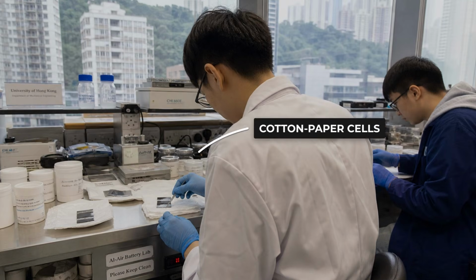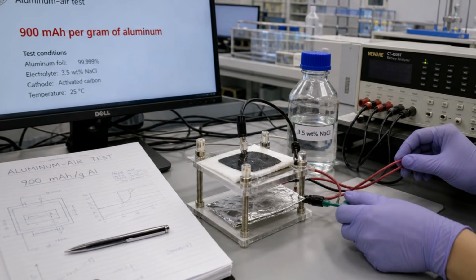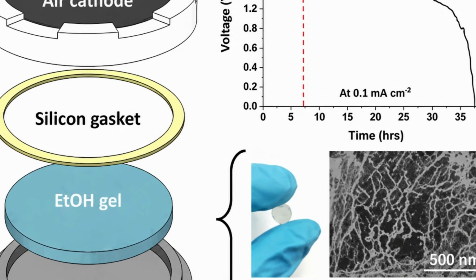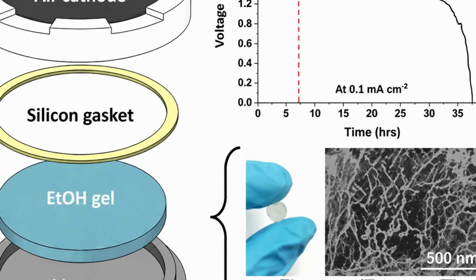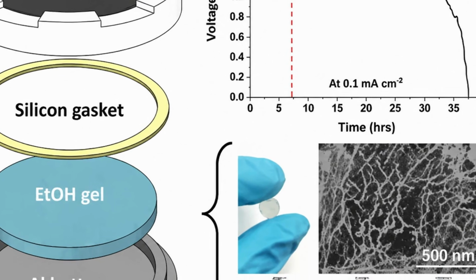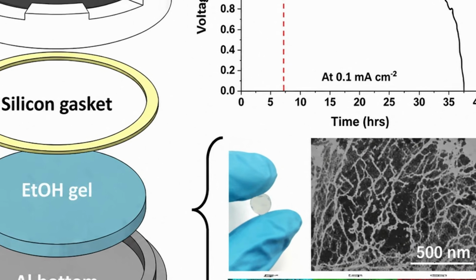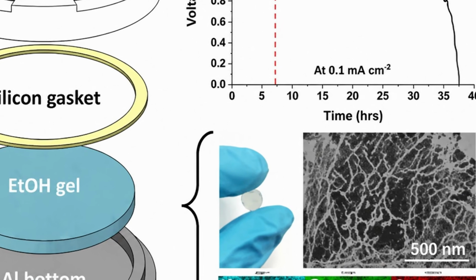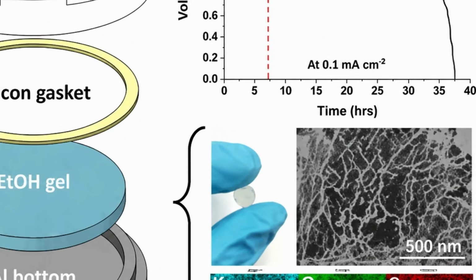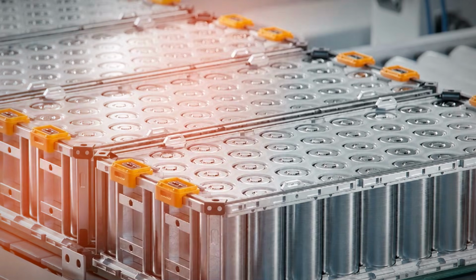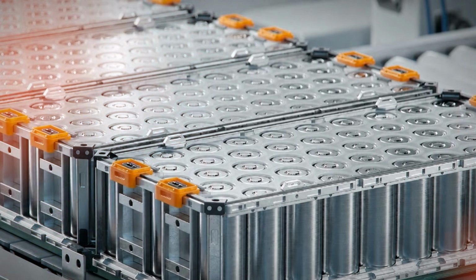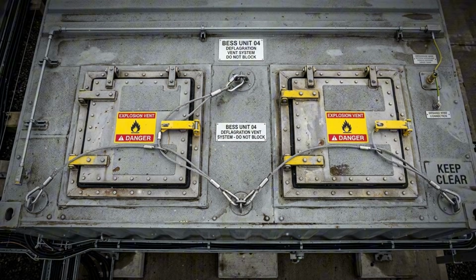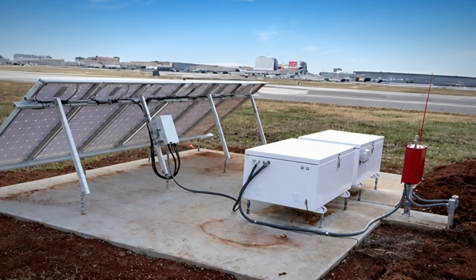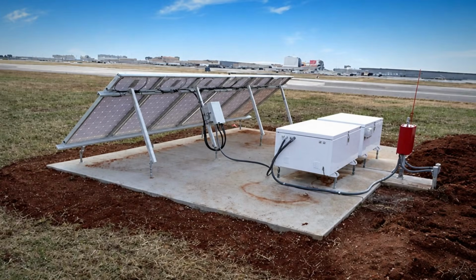Laboratory work has been pushing at the boundaries as well. A group at the University of Hong Kong built cells on cotton and paper substrates, reaching around 900 milliamp hours per gram of aluminum, and other researchers have taken quasi-solid-state designs toward 4.56 kilowatt-hours per kilogram under test conditions. Look across all of it, and one requirement keeps repeating. Every application involves a long period of doing nothing, followed by one reliable discharge.